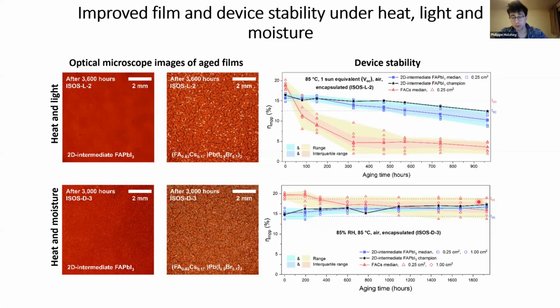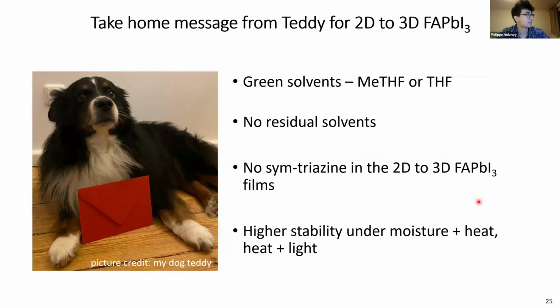So I have another little summary, just in case. So there's a little take-home message from Teddy. We're using green solvent, methyl THF, but it's also possible with THF. We have no residual solvents. There's no sym-triazine forming in those 2D to 3D FAPbI3 films, and we find a higher stability under moisture, heat and light.